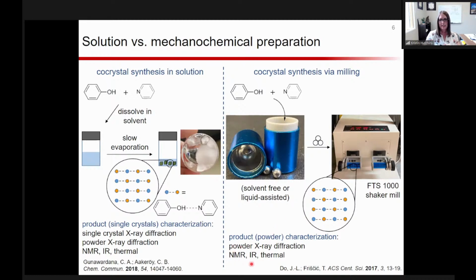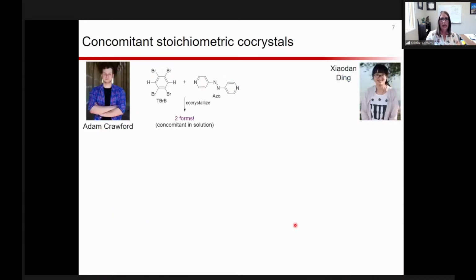And then you can do the same things, like spectroscopy and thermal properties. The only difference is typically you are not going to get single crystals by this method. You're not going to have crystals that are large enough to do single crystal X-ray diffraction. So typically we're working with powder diffraction. And so the first story I want to tell you today is related to our thermal expansion work, and then I will get into the pharmaceutical work.